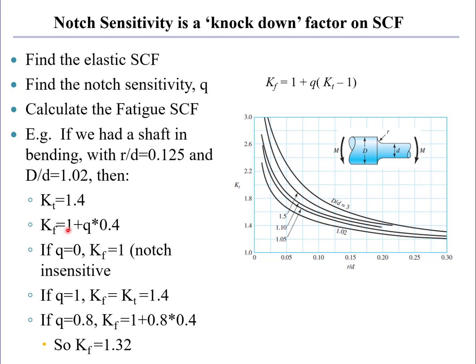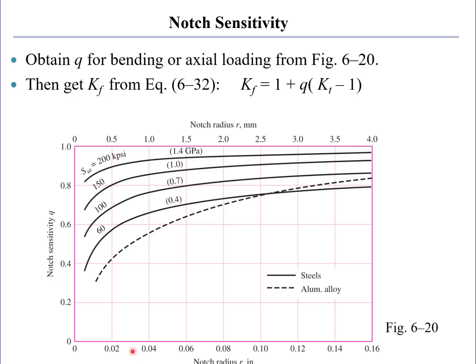stress concentration factor. As we said before, if the material is notch insensitive, Q is 0, this second term falls out, and the fatigue stress concentration factor is just 1. There's no stress concentration. If Q is 1, the fatigue stress concentration factor is simply equal to the elastic stress concentration factor, which would be 1.4 for the case I just described. But if Q is 0.8, I take 1 plus 0.8 times 0.4 and that gives me a fatigue stress concentration factor of 1.32. This is a huge burden to do this sort of thing.